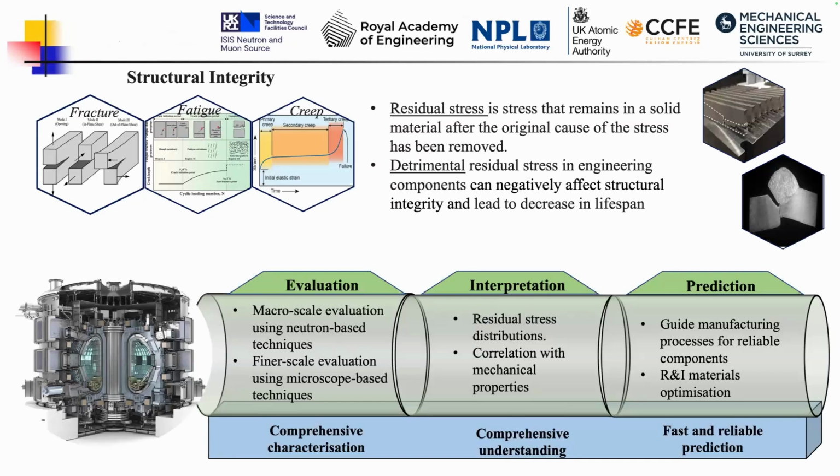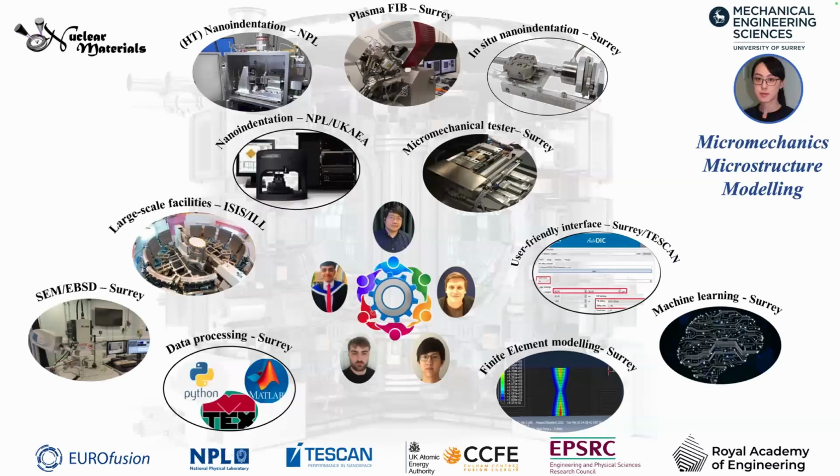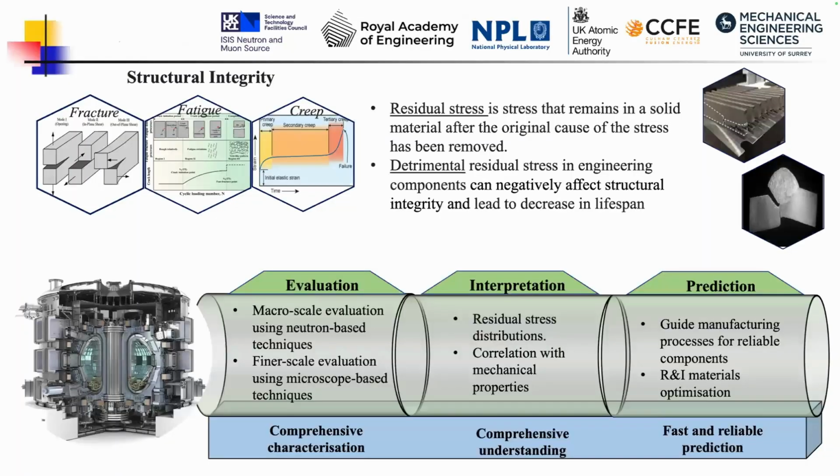As biological systems ourselves, we have benefited from having residual stress. For example, we have tensile residual stress in most soft tissues, like the skin, to maintain integrity but at the same time remain functional. Similarly, hard tissues usually have a layer of compressive residual stress, which prevents crack initiation and propagation. But in the context of the engineering industry, the question is really, do we suffer from detrimental residual stress? How are we going to cope with that?